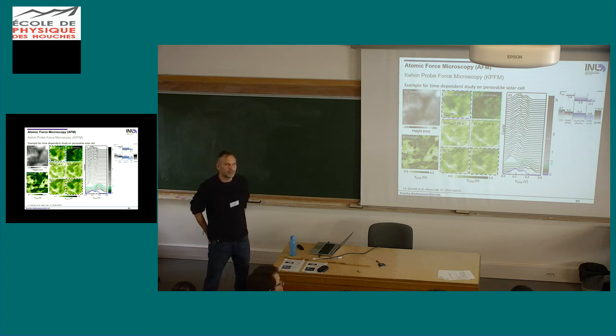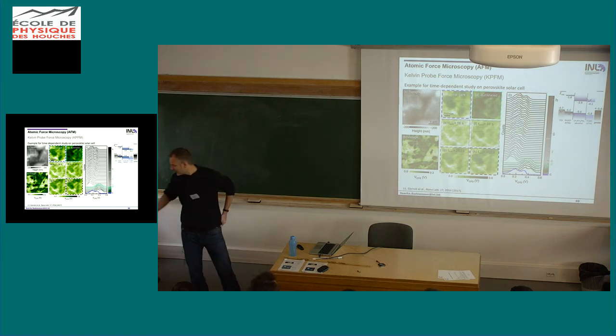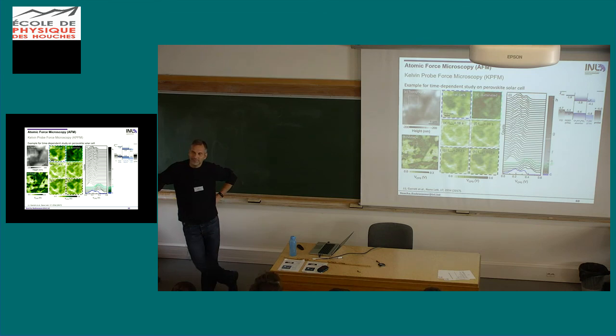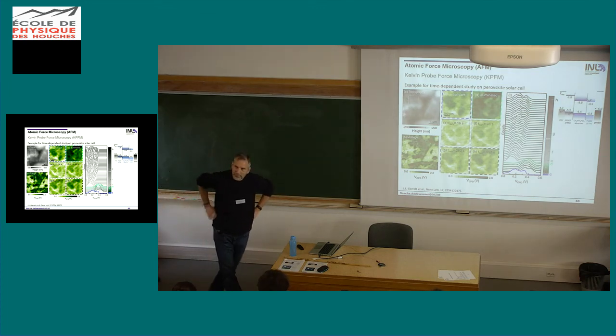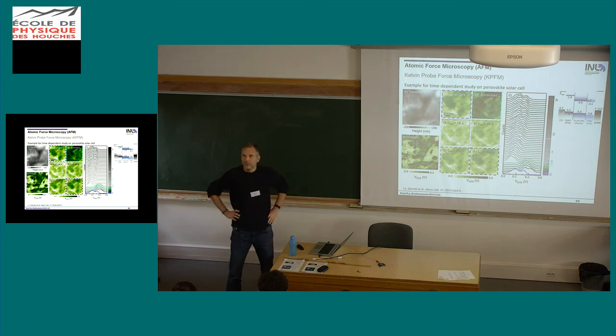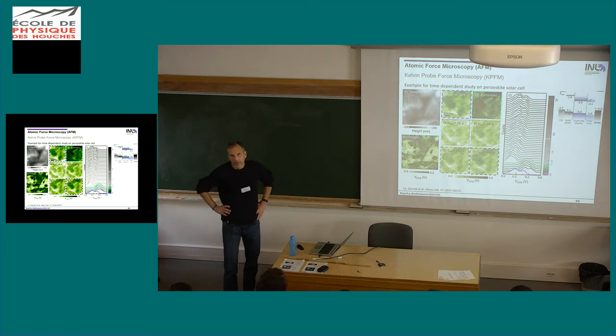Other questions? Yes. I have a question on the CIGS result that you showed with this alkali selenite at the grain boundaries. You mentioned you have a large band gap. Of course these phases are known, but I'm not sure how stable they are to oxidation. And also about the conductivity. I know they have been reported, and in principle they can be beneficial, but unless they block the current between the grains, they can also cause some other problems. So do you know about the stability or conductivity of these layers?